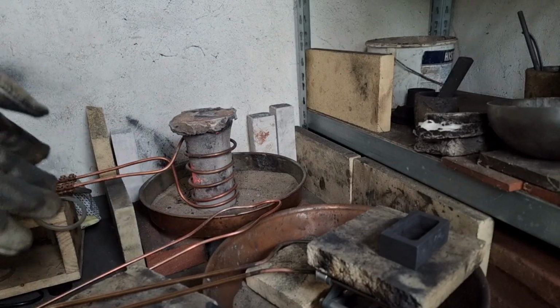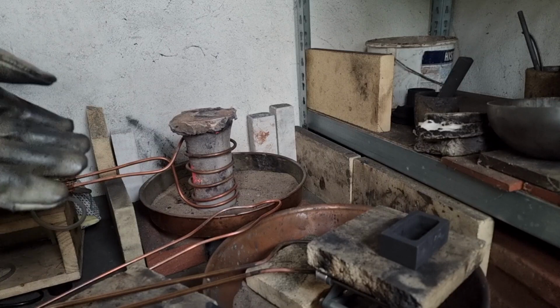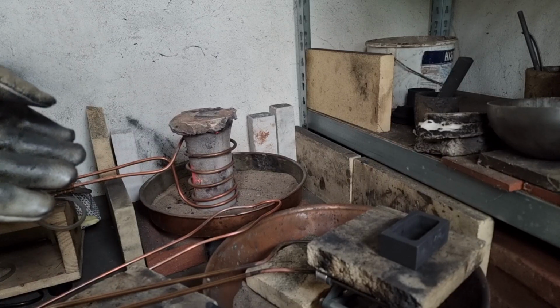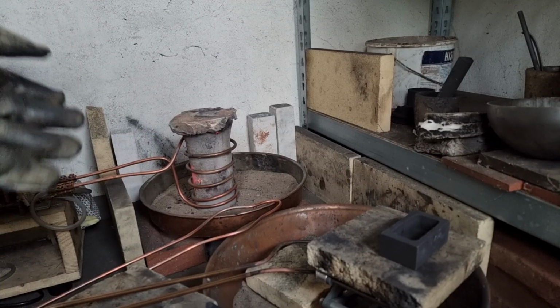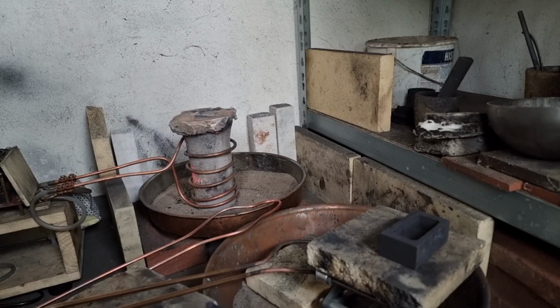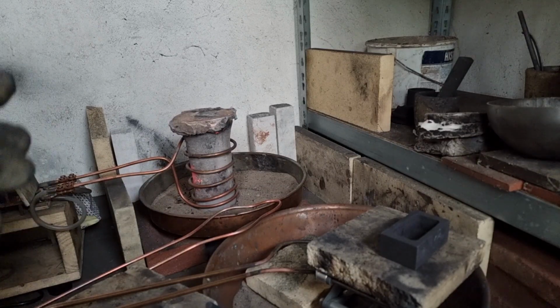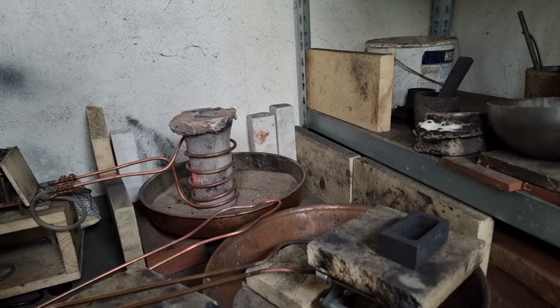You should not heat that iron too hot. There's always a risk that you burn off the carbon if you get it too hot. So you want to get it just right. Of course, the best would be to have a gas forge or something like that, so that you have a really reducing atmosphere. But I don't have that. I have only my small workshop, and I don't want to have propane flames rolling out of my garage here.